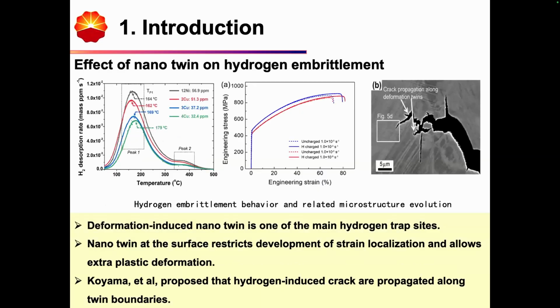If we focus on the nanotwin itself, several TDS results have revealed that deformation-induced nanotwin is one of the main hydrogen trap sites in the material. It changes the partitioning of hydrogen during testing. Therefore, nanotwins that form during testing, especially near the surface, restrict the development of strain localization.